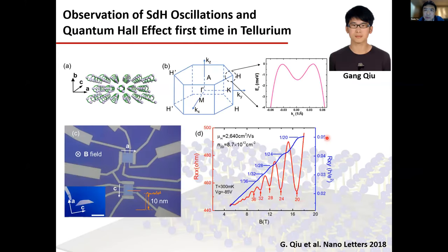All right. So now we move to more physics, since this workshop is about quantum materials. The valence band at this H point is highlighted like this. This has been known since the end of the 70s. People call it a camel structure for the valence band. In the recent literature there's a lot of confusion, because we are particularly interested in topological properties. There's some discussion about the Weyl nodes, but they are deeply inside the valence band. And some of the Weyl nodes happen because of high pressure or other factors, which I will talk about later.